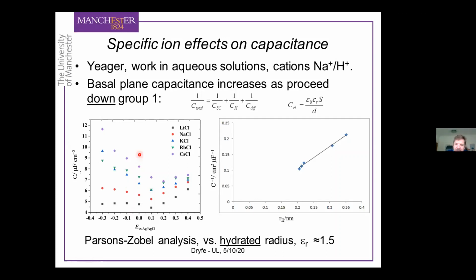And we can try and analyze that in a very, very naive way. As I said, we're working at high electrolyte concentration, so we can neglect this term, but we can say we have a space charge term and a Helmholtz term in series. And if we plot the reciprocal capacitance against the size of the ion in some way, doing this kind of Parsons-Zobel type analysis, then the gradient of this plot tells us something about the relative permittivity of the water that's in the monolayer of ions adsorbed on the surface.